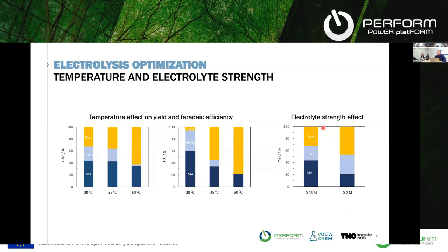Similarly, we also looked at the electrolyte strength. I said that we are working in acidic conditions. So if we use a 50 millimolar or 200 millimolar sulfuric acid electrolyte, then we also see that at 50 millimolar we get better results compared to the 200 millimolar. When you combine all this information gathered from very small setups, typically